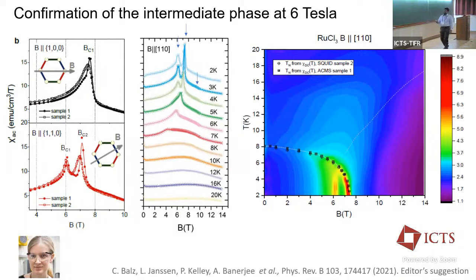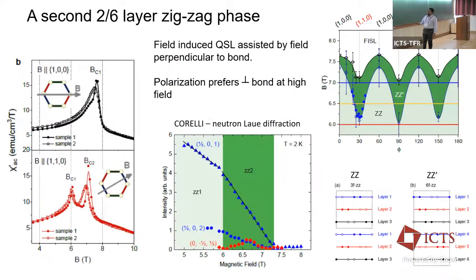Using AC susceptibility, we tried to understand what these phases are. We found that between 6 and 7 Tesla, there is this nice phase with 2 kinks in the AC susceptibility, measured by beautiful data by Paige Kelly. For some time, we wondered if that's the phase where you should see this quantum spin liquid behavior, but it was not that, as we figured out. Using an instrument called CORELLI, which is a Laue diffractometer, we found that you have a new magnetic order coming up right at that phase. So that's actually a long-range ordered phase. The phase where we really don't have any long-range order is beyond 7.3 or 7.5 Tesla. So that's probably the more interesting phase.